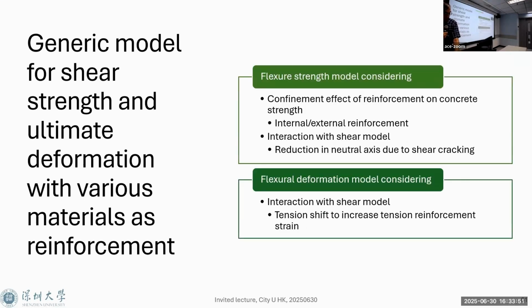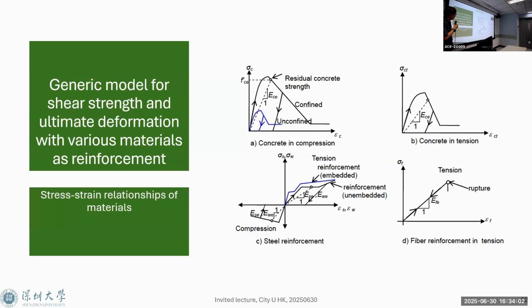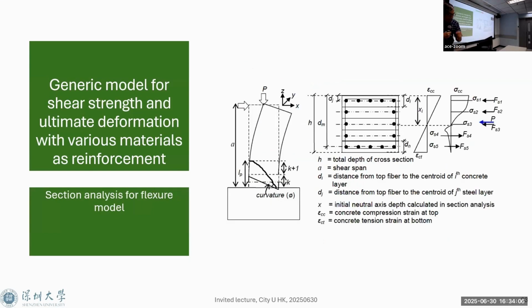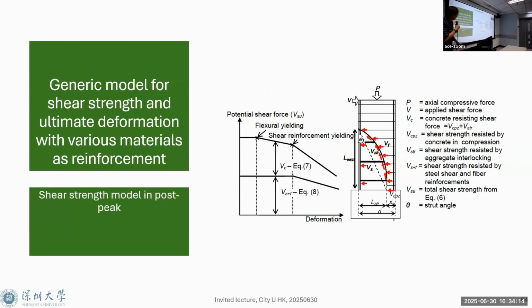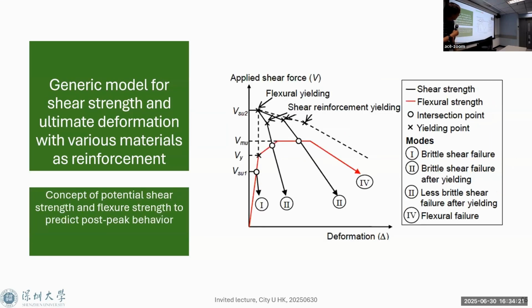Probably I may not go into detail. And also a flexural strength model and a flexural deformation model. So we combine them, considering each material's stress-strain relationship, and we utilize typical sectional analysis, and we consider the contribution of each component to the shear strength. Then we have the concept of potential shear strength depending on the deformation. So once we have greater deformation, meaning greater strain development and less stiffness, then the remaining shear capacity becomes less.